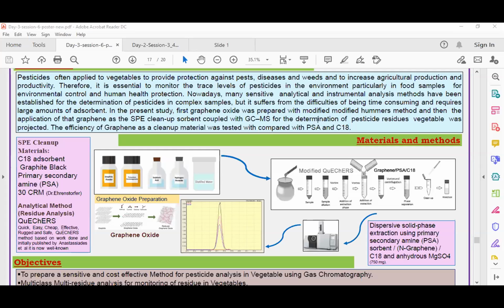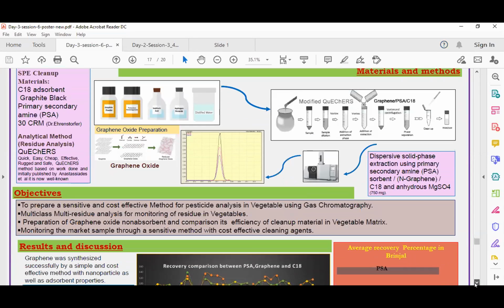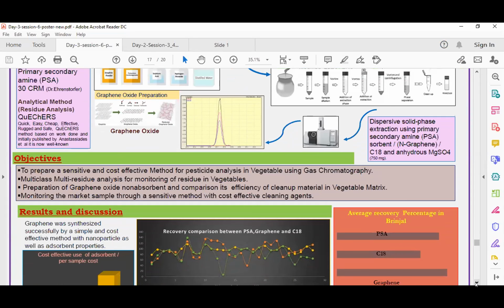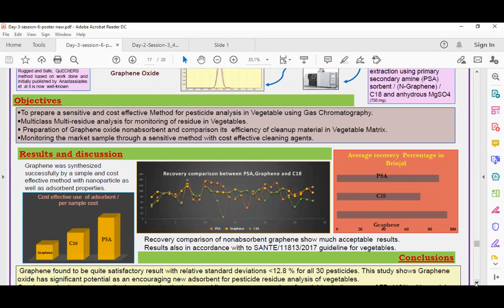and then we reduced the volume also, and compared the recovery study with C18 and primary secondary amine. The recovery criteria shows that most pesticides show good recovery percentage with primary secondary amine and graphene also, whereas C18 shows a downward curve. The QuEChERS method recovery studies show that C18 has a very low percentage of recovery compared to PSA. In the cost-effective calculation, PSA is almost 12,000 to 20,000 per gram, according to purity. But graphene oxide is a very homemade nano-absorbent that can be used as a cleaning reagent.